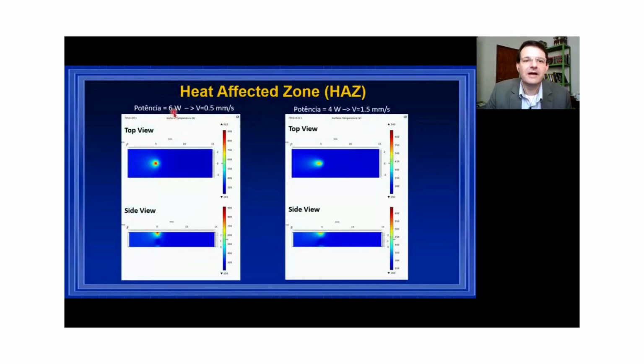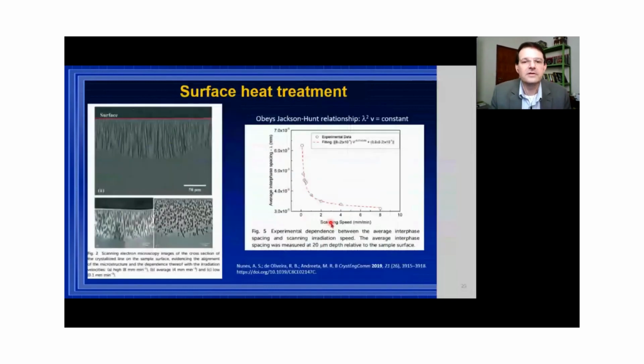Of course, if you have a very high power and a traveling focused beam at low speed, you create a very large heat affected zone. On the other hand, if you reduce the power a little bit but go very fast, you can see that the depth of the heat affected zone decreases very much. So it's interesting to do experiments on that.